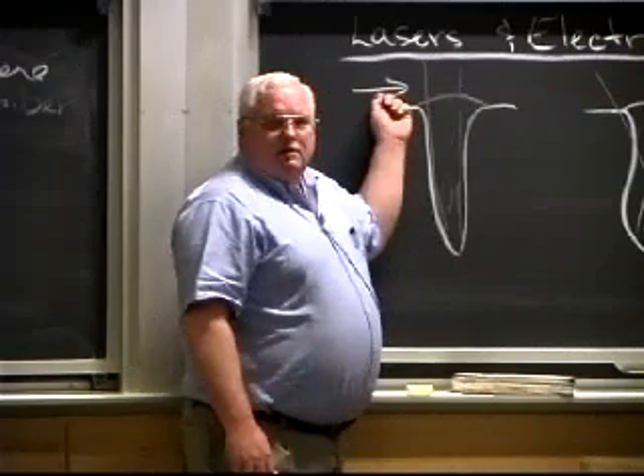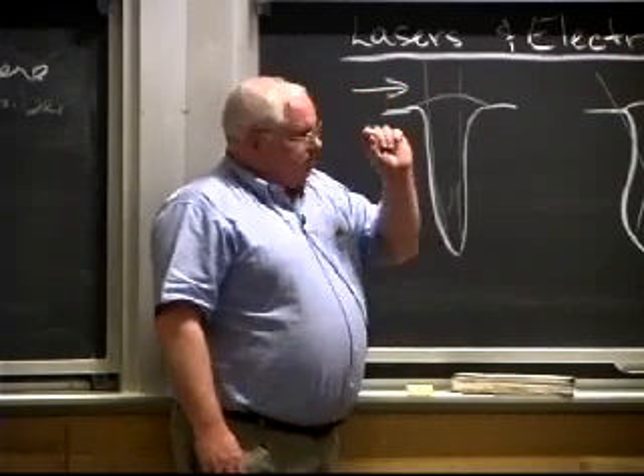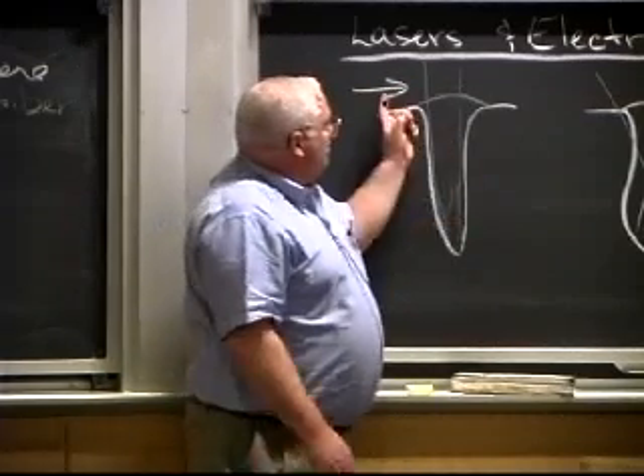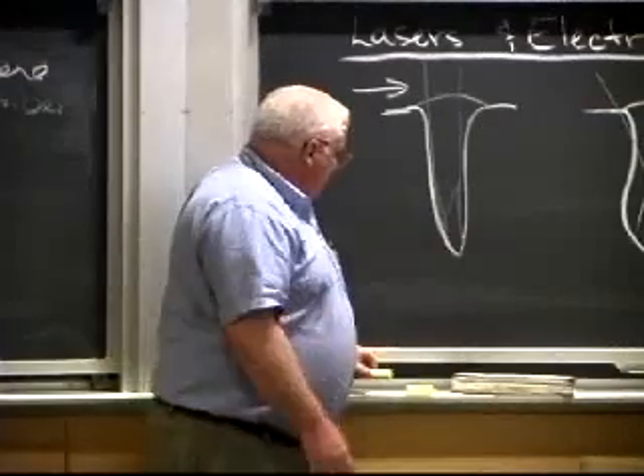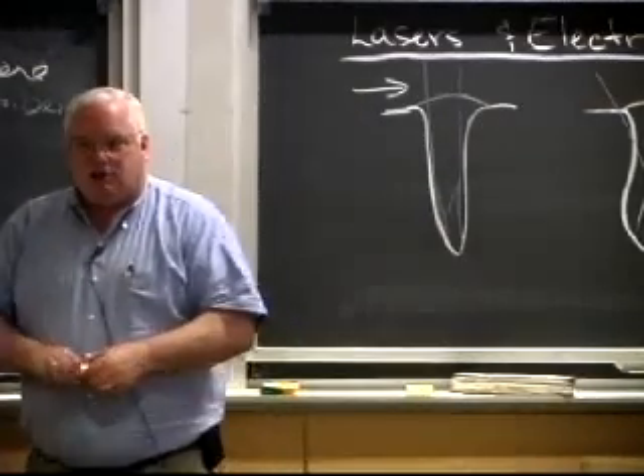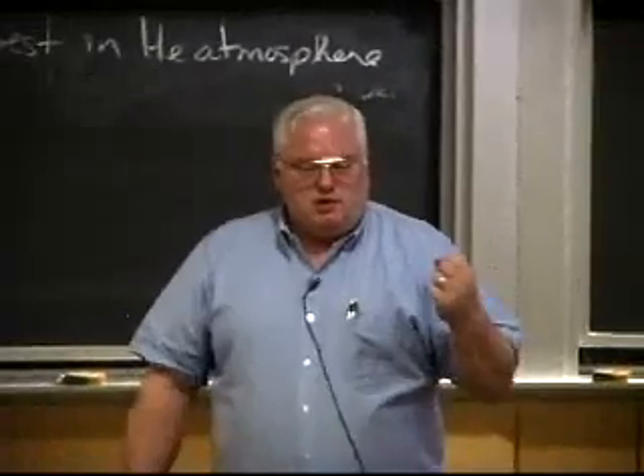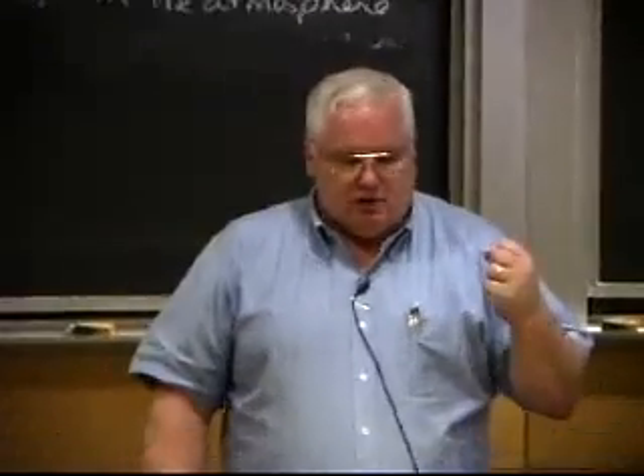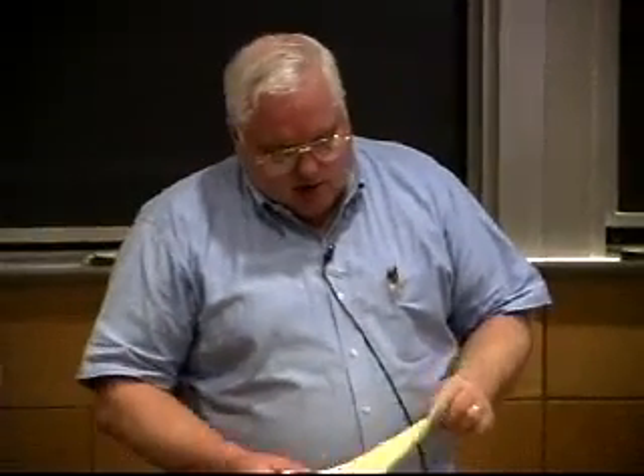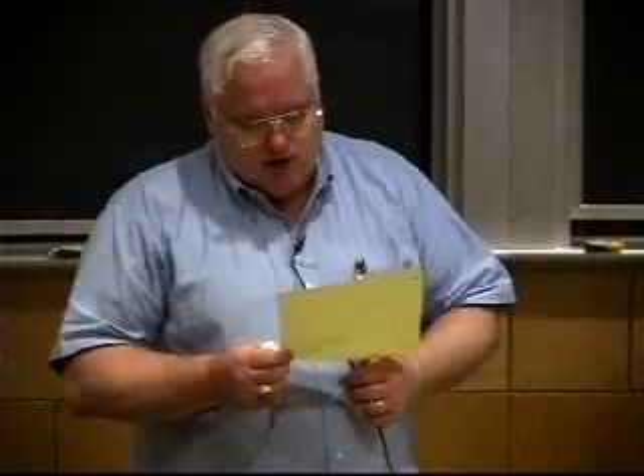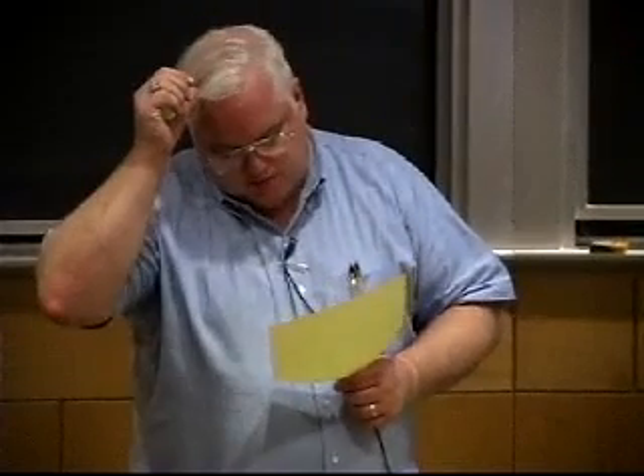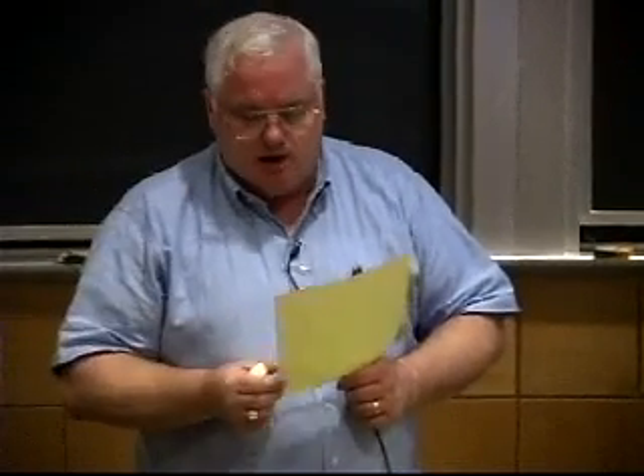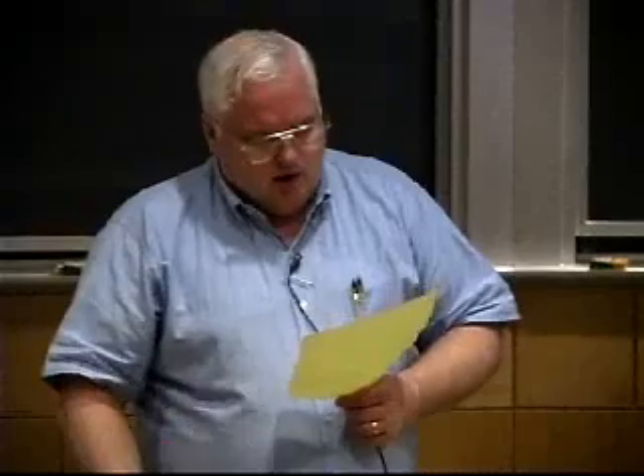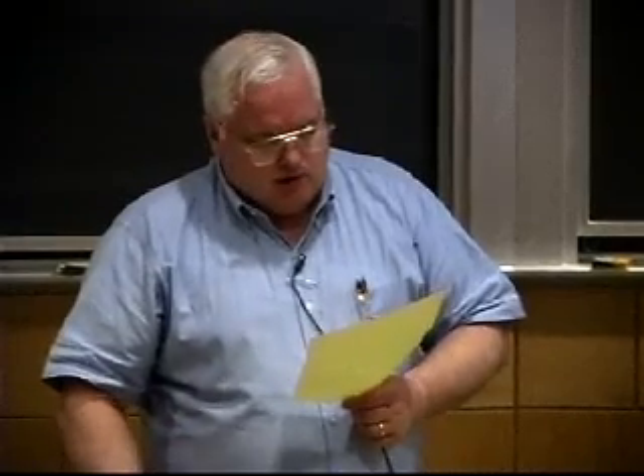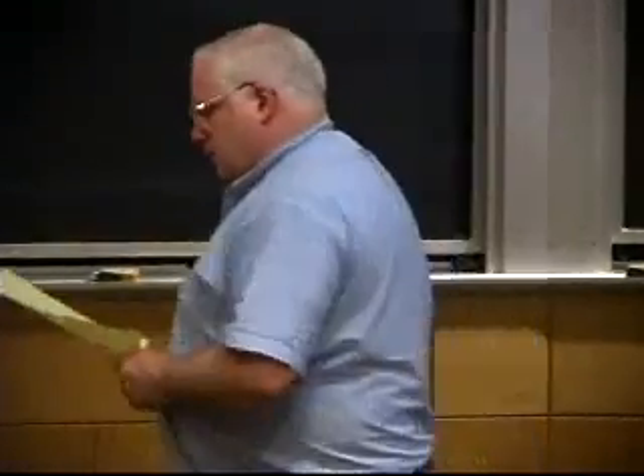If you can afford the helium, it doesn't take much. Typically, this is just a little needle of helium. You blow the helium across here, and since helium has the highest ionization potential of the inert gases, it will hold on to those electrons to higher temperatures than anything else. And so it turns out laser welding is best in a helium atmosphere, okay, because you can ionize either the argon or the air and generate free electrons and block your beam, okay?